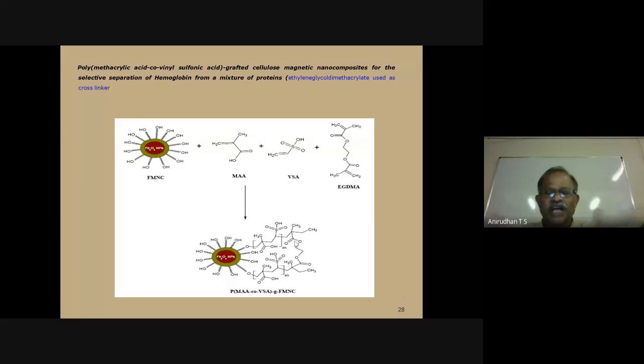original cellulose. This material can be utilized for a wide variety of applications, especially to capture metal ions or that type of cations, etc. So what I have concluded, I have prepared this material especially for capturing with highly specific selectivity. I always remember this because this particular material has two different acid groups, COOH and SO3H, with different pK values. With the different pK values, you can ionize this, sulfonate resonance structure, carboxylate resonance structure.